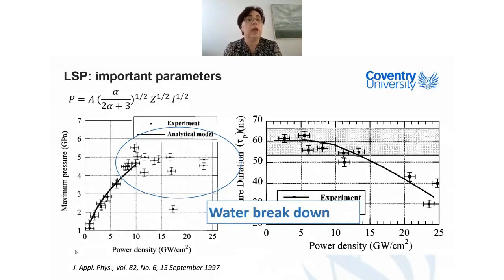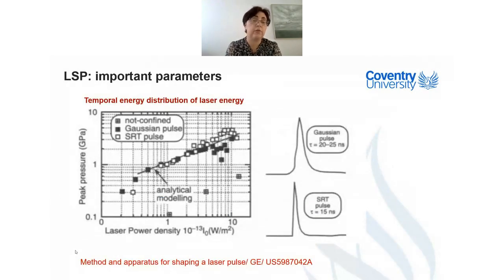Another important parameter: if we look now and say that pressure depends on power density, everybody would say, okay, let's increase power density to infinity and I get whatever I want for maximum pressure inside the material. But unfortunately, that's not true. And it's not possible, as you can see from the graph on the left side. Around 8 to 10 gigawatt per square centimeter, we get some effect which stops us from increasing maximum pressure in the material. And at the same time, pressure duration inside the material starts decaying. The reason for that is called the water breakdown effect.